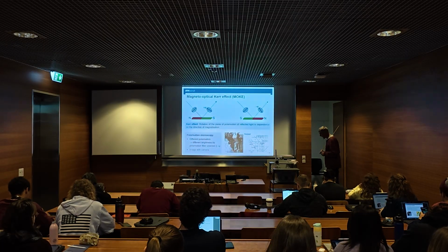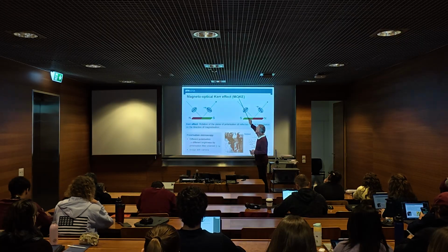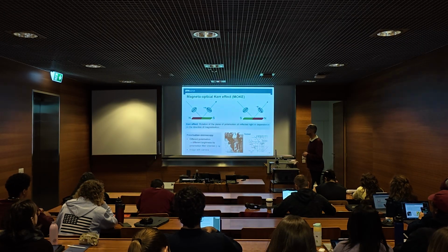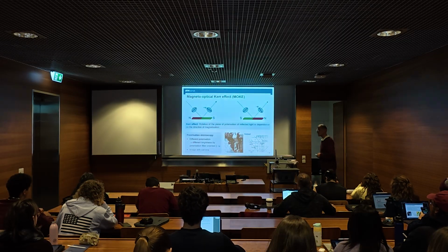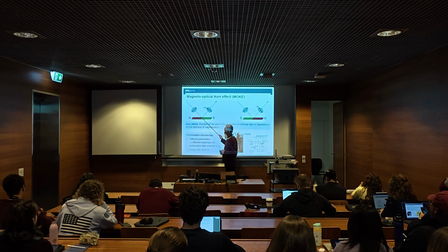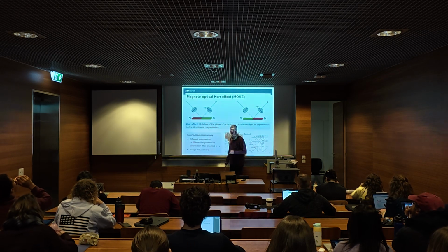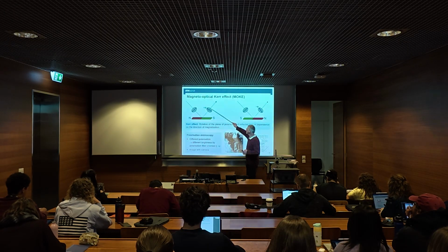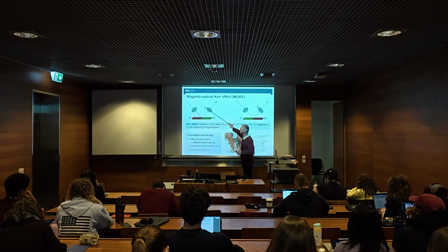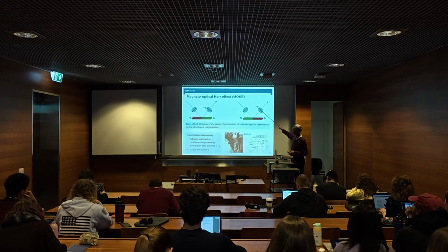Now, how do you see magnetism and the distribution of magnetization in a sample? Then the technique that is mostly applied is the magneto-optical Kerr effect. So you again take polarized light, you reflect it on a magnetized sample, and then the polarization of the light is rotated by the magnetization. And the nice thing is that if it's plus magnetization, or south pole or whatever, you get plus rotation in your angle, and if it's minus magnetization, it's minus rotation.